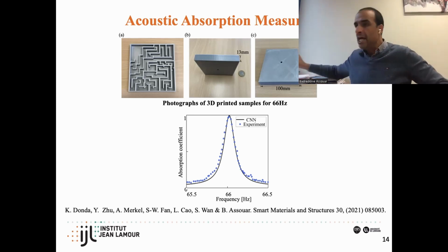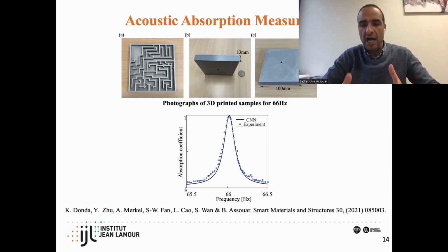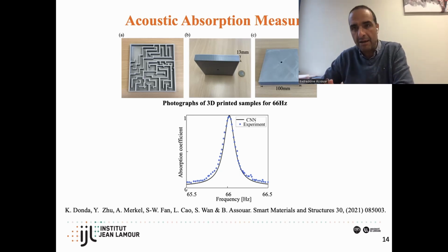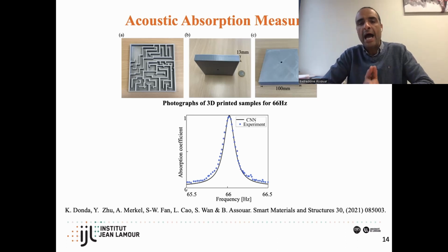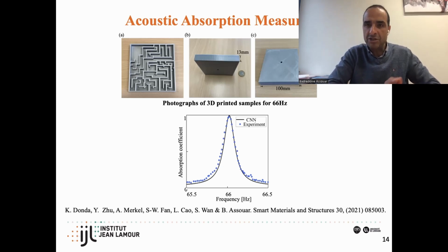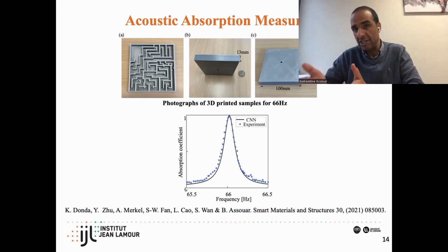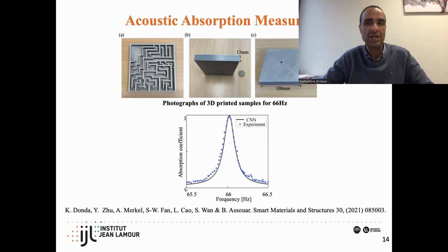The second question about the CNN, actually what we earned is that the idea was how we can go toward lower frequency than what we get, about like 60 or 100 or something like that. And we were hoping that maybe the structure that the CNN can propose could simultaneously give us some lower frequency, which actually it did give, the 38 hertz. But we were hoping that maybe we can get broadband, and we didn't get it. But still, it's a very important approach, because if you have a stable CNN, it's by far much faster than the finite element method. It's a fraction of a second.